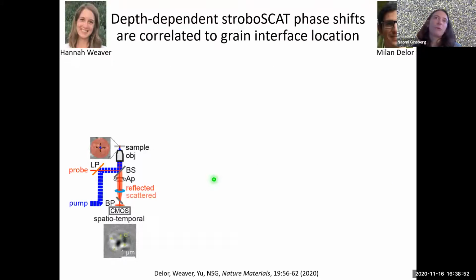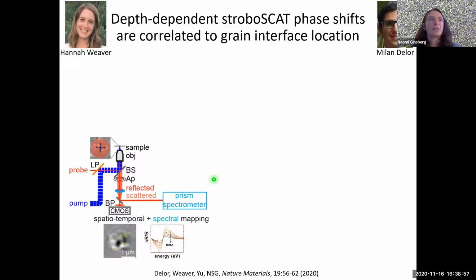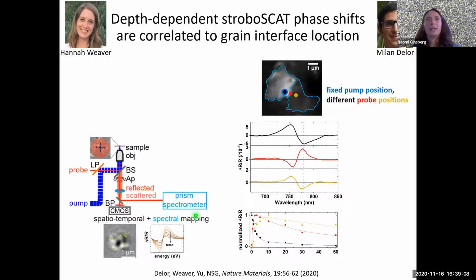Now let's see, we corroborated this hypothesis by performing spectral interferometry around the band edge. So basically dispersing light spectrally in a spectrometer instead of taking a picture of it like we typically do, but in the same instrument. And if we excite on one side of an interface here and we probe either on the same side or on opposite sides, you can see that the signal that we measure spectrally has the same phase, whereas the phase is different when we measure over top of an interface.